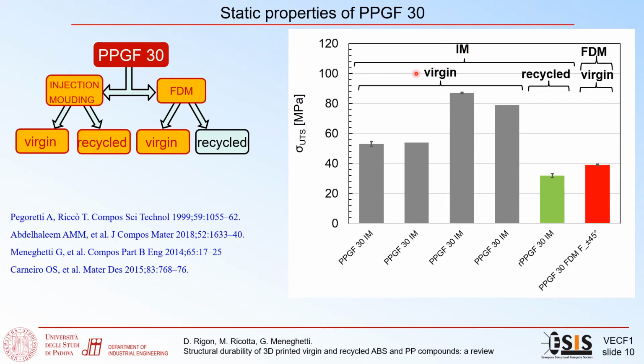Finally, we have the static properties of PPGF 30. Analyzing the injection molding virgin PPGF, we can observe different values of the UTS due to the different fiber lengths in the material. The recycled PPGF 30 produced by injection molding shows a UTS lower than the lowest virgin injection molded PPGF. No information about fiber length was reported in the original paper, so no further conclusion can be drawn regarding this. Analyzing the FDM virgin PPGF, even in this case, with a raster orientation of plus minus 45 degrees, the UTS is lower than the lowest virgin injection molded PPGF.